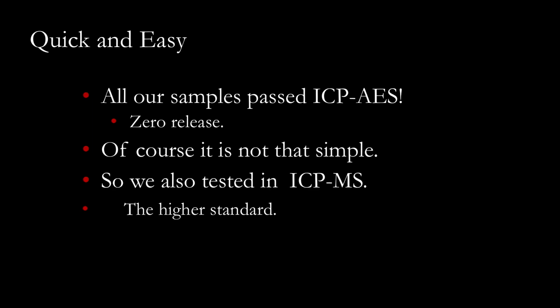So when we sent our samples off to get tested, we actually came back with 0 results from ICP AES. But it was observed on the tiles that there was physical degradation as the copper amount increased. We knew that something was leaching out. So we had to upgrade our test protocol to ICP MS, the higher standard, and we began to get results. Here come the wall of numbers. Buckle in. It's a little much.